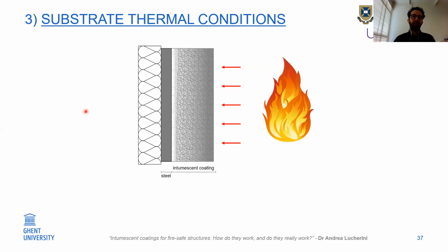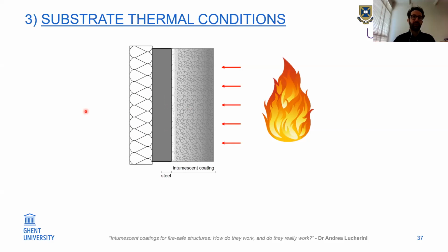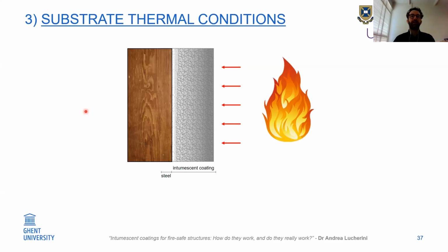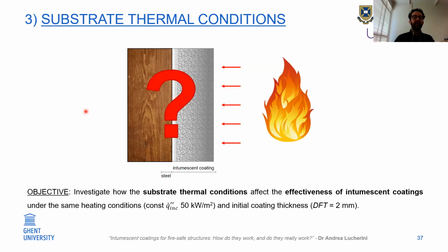The question now is, what happens if I have a thicker plate, so a thicker thermal mass? And also I was wondering what happens if I apply my intumescent coating on a steel substrate versus a timber substrate that has completely different thermal and physical properties. So in this study, I wanted to investigate how the substrate thermal conditions affect the effectiveness of intumescent coatings under the same heating conditions, and I just picked 50 kilowatts per square meter, and under the same initial coating thickness, 2 millimeters, okay, DFT.